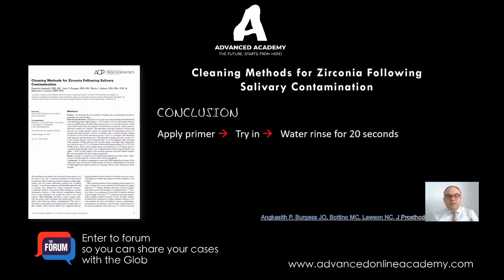That will clean the salivary lipids and protein as well. Either you apply your primer, try it in, and then water rinse for 20 seconds. That's one of the recommendations, because if you think about it, if you apply the primer on the zirconia first and then you try it in, the primer is there to protect the intaglio surface from contamination. All you have to do is rinse it off with water. But if you have IvoClean, you can try it in, clean it with IvoClean, or sandblast it, and then apply your ceramic primer.